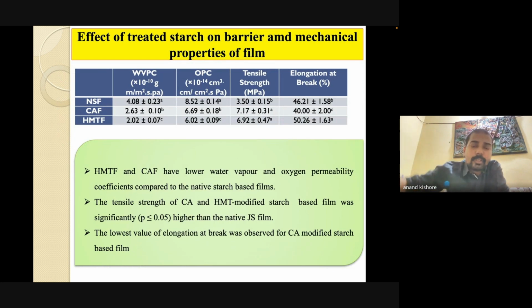The water vapor permeability coefficient and oxygen permeability coefficient are very important parameters which affect the shelf life of the packaging film. After modification, there is a decrease in the water vapor permeability coefficient. Because we modified with citric acid, we have cross-linking, and we found in the water solubility and swelling power of the starch that it reduced the hydrophilic characteristics. So maybe that is the reason for the reduction in water vapor permeability. Now the oxygen permeability coefficient is also an important parameter. Again there is a decrease, because after modification there is a rearrangement of the amylose and amylopectin. We also see the same structure, a uniform structure and cluster formation. So they make a strong bond between the molecules, and the diffusion path is reduced in this case. That's why the WVPC and OPC are reduced.